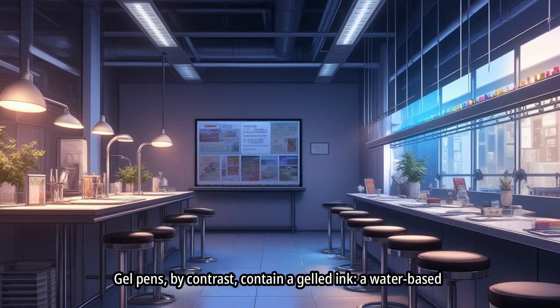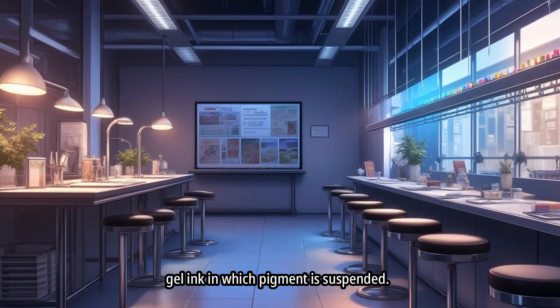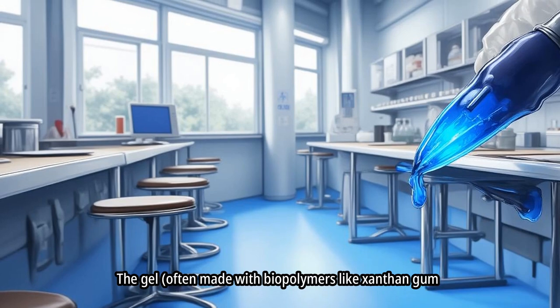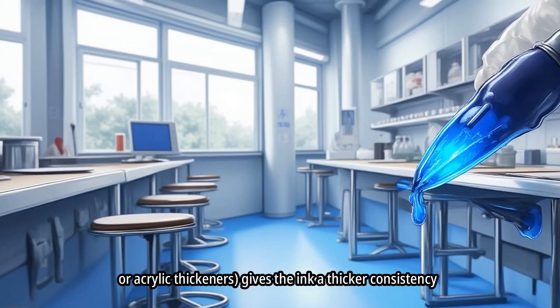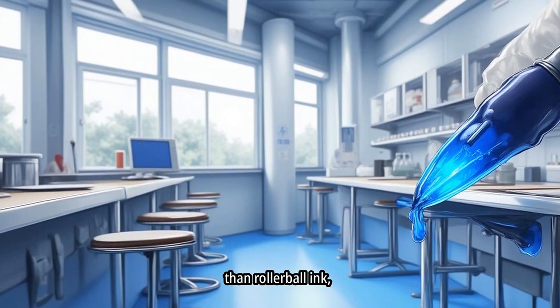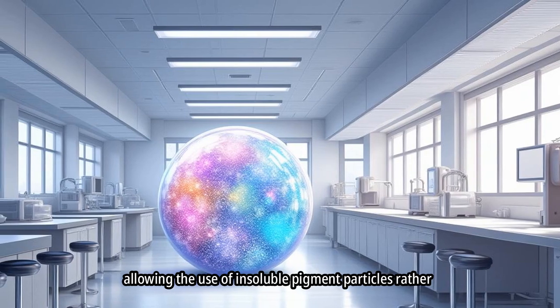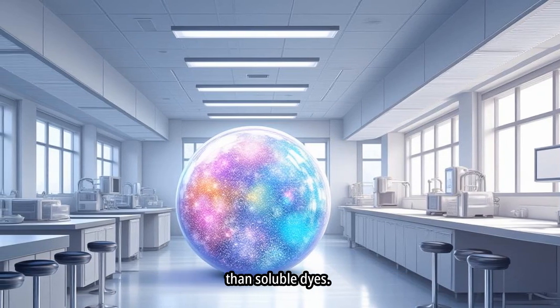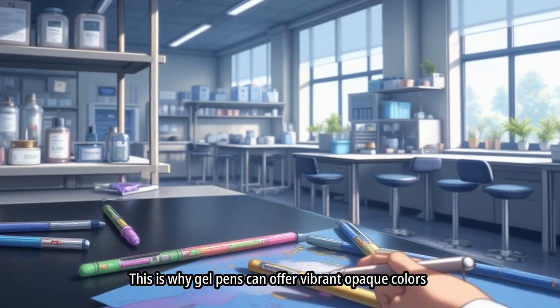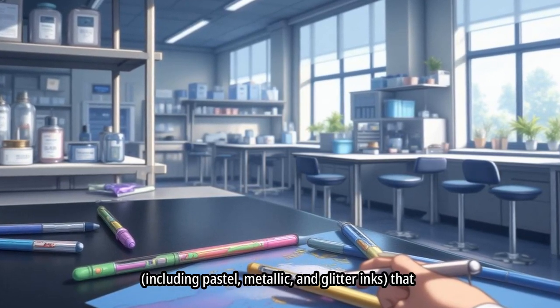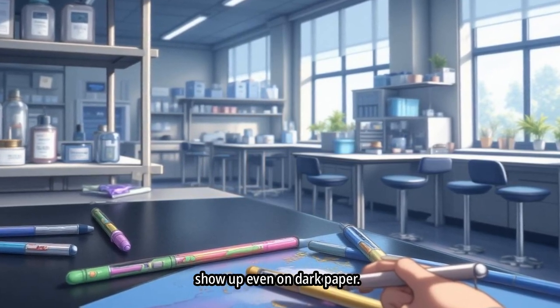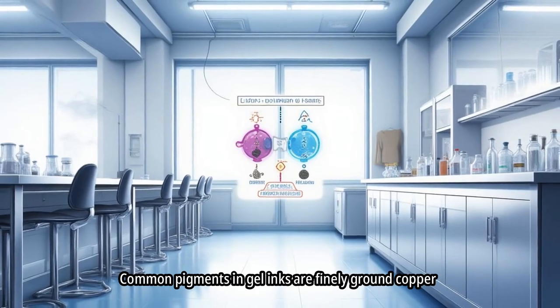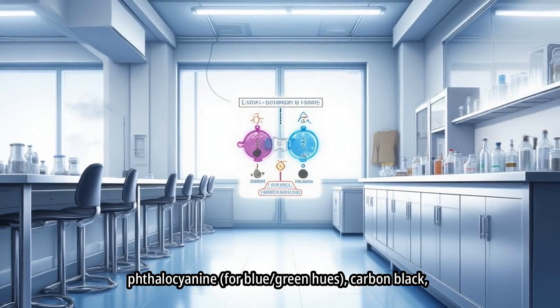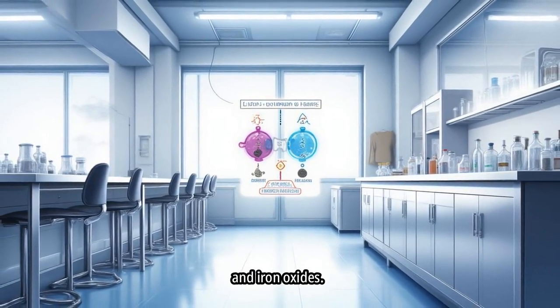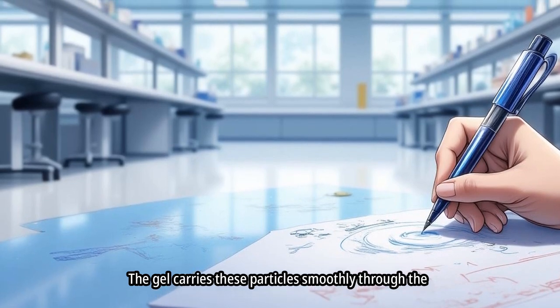Rollerball inks are usually dye-based and may contain additives similar to fountain pen inks, wetting agents, etc., but in a more free-flowing formulation. Gel pens, by contrast, contain a gelled ink, a water-based gel ink in which pigment is suspended. The gel, often made with biopolymers like xanthan gum or acrylic thickeners, gives the ink a thicker consistency than rollerball ink, allowing the use of insoluble pigment particles rather than soluble dyes. This is why gel pens can offer vibrant opaque colors, including pastel, metallic, and glitter inks, that show up even on dark paper. Common pigments in gel inks are finely ground copper phthalocyanine for blue-green hues, carbon black, and iron oxides. The gel carries these particles smoothly through the pen and onto paper.